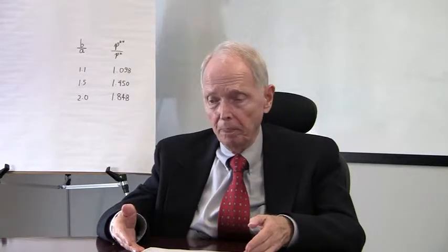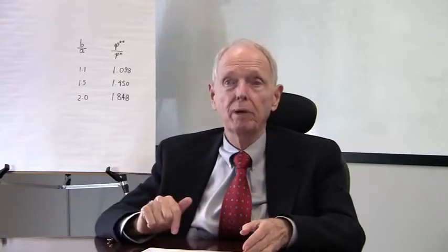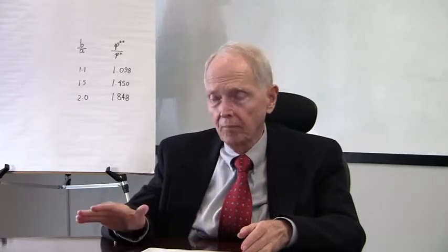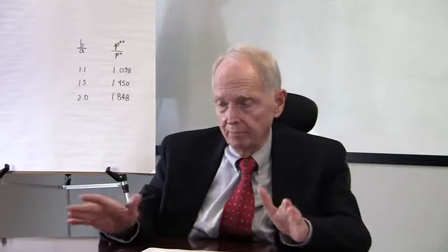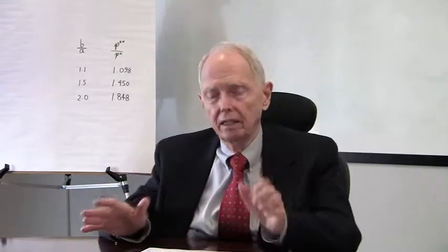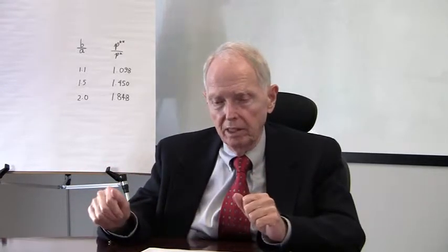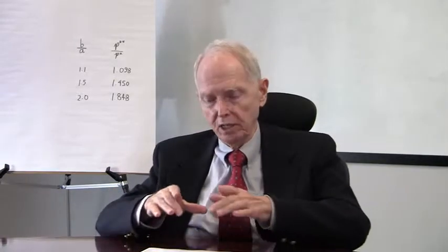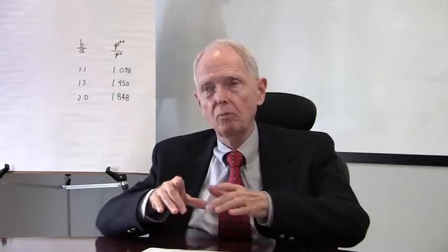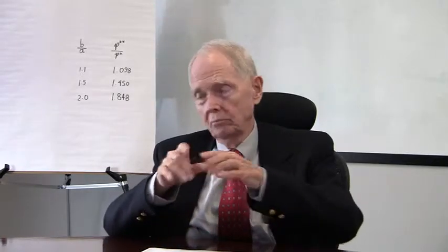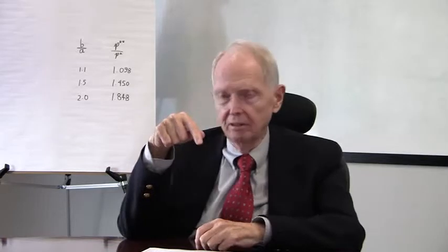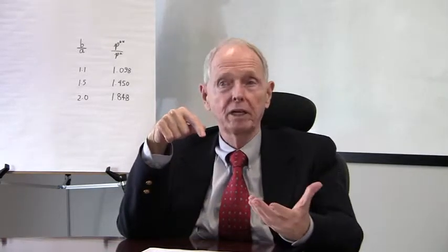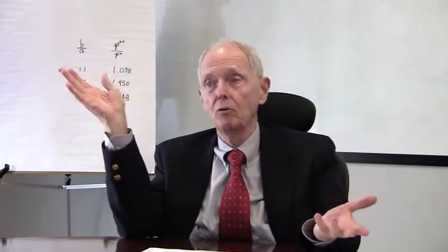Constant slope, it's got to have 0 on the boundary, because that derivation had nothing to do with plasticity. And so I'm building kind of a little tent here. In the case of the torsion problem, if I just kept twisting and twisting and twisting, I would just have a constant slope figure that would be heading for the top, which would correspond to the angle of twist being infinite. And I would form a cone.